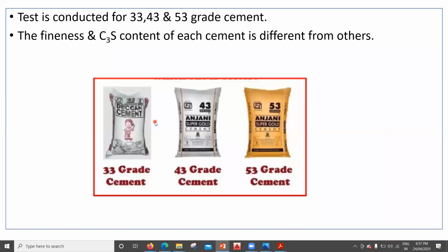Whatever we have done so far, there are different grades of cement, right? We have 33, 43, and 53. So what changes will happen in 33, 43, and 53? The first change is the fineness. The 33 grade cement is less fine in comparison to the 43 grade cement, and 43 grade cement is less fine in comparison to 53 grade cement. The second is the tricalcium silicate content. The tricalcium silicate content is less here, so the strength gain is also less. But in 43 grade cement, the tricalcium silicate is more in comparison to 33 grade cement. That is the reason 43 grade cement will get more strength. And 53 grade cement will have more tricalcium silicate content in comparison to 43 and 33. That is the reason we get more strength in 53 grade cement.